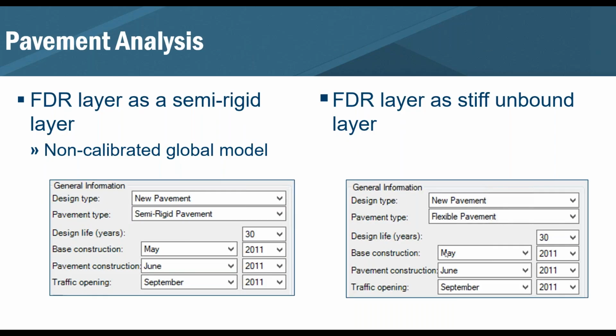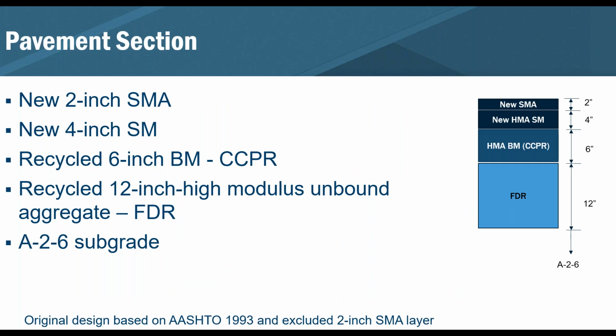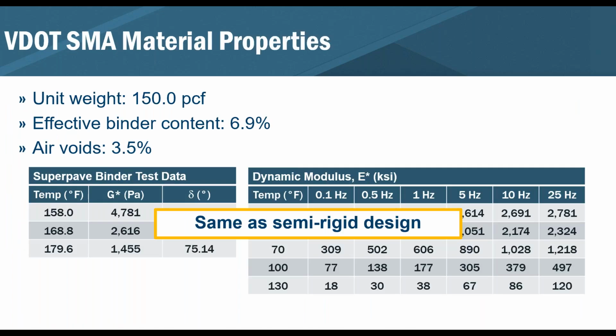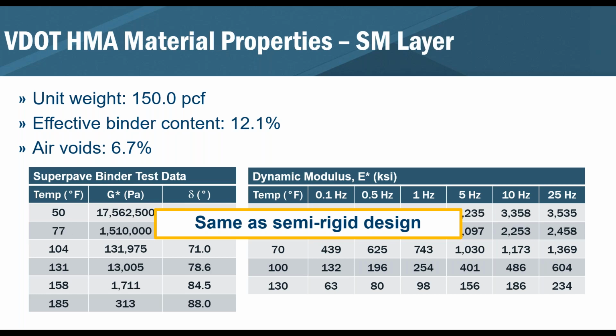All right. So now looking at it as a stiff unbound layer, and I'll do some comparisons at the end as well. It's a similar type of structure. Again, the 2 inches of the SMA, 4 inches of the asphalt surface mix. The recycled layer is still an asphalt base material. Now we're going to model that 12 inches of FDR as a high modulus unbound aggregate layer, sitting on top of the A2-6 subgrade. Won't get into boring you again with the same details, but the SMA material doesn't change. The HMA under the SMA layer doesn't change.